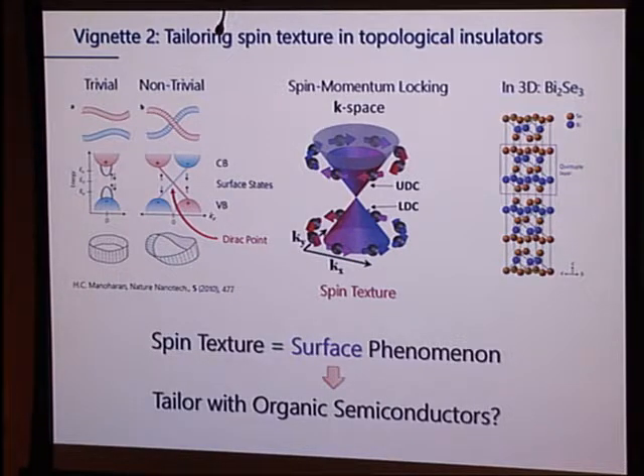Now, if I introduce strong spin-orbit coupling, and I can do that by going to elements that have a high nuclear charge, for example, you see here in bismuth selenide, there's bismuth and there's selenium in there, then that spin-orbit coupling will mean that my bands are splitting up into spin-up and spin-down parts, and they are no longer reflection symmetric with respect to the zero momentum point, meaning an electron out here must have a different spin than an electron over there. And this gives rise to this topological protection, meaning that electrons up here cannot easily scatter because there's no place they can go to.